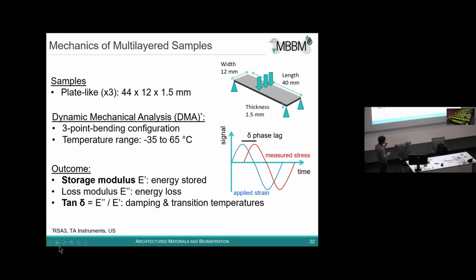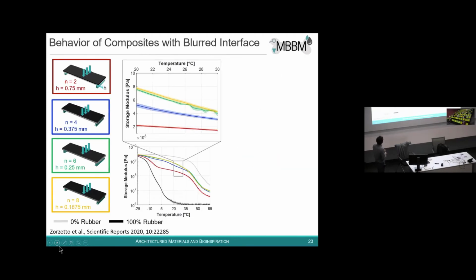For the dynamic mechanical analysis, we basically use a 3-point bending configuration, and we scan the behavior across different temperature ranges to see what is happening across the phase transitions. And the main output that we consider is the so-called loss modulus and the tangent delta, which are typical parameters to describe the dynamic behavior of those polymeric systems. Now I will just show you this. So this is basically a plot of the storage modulus.